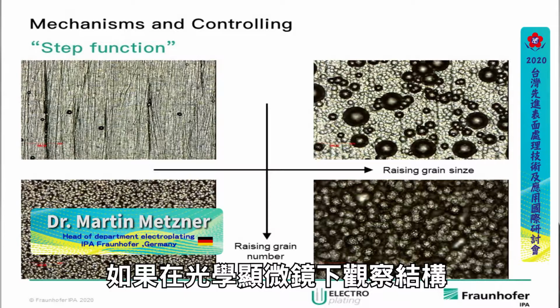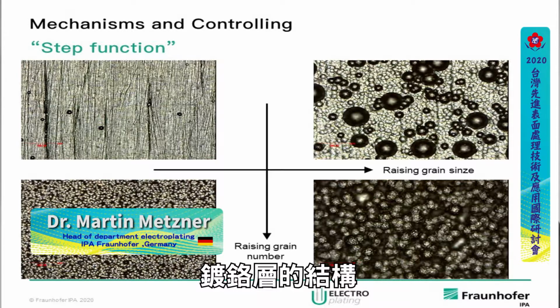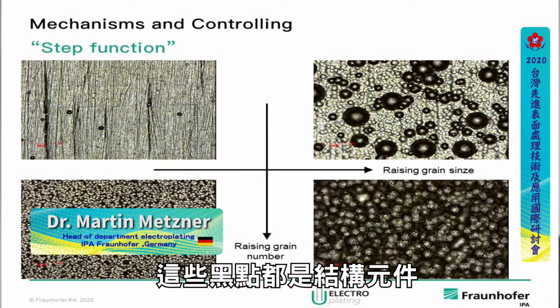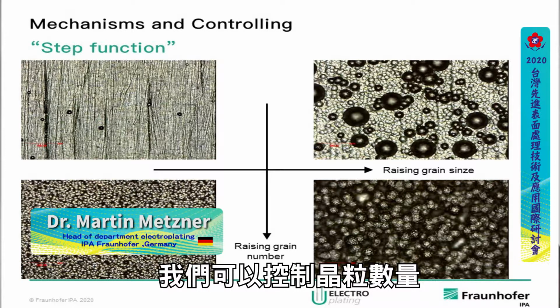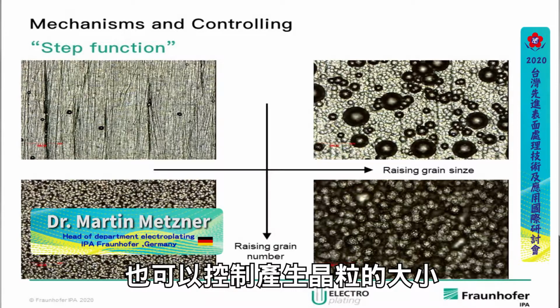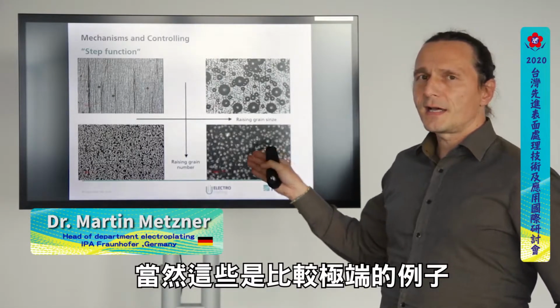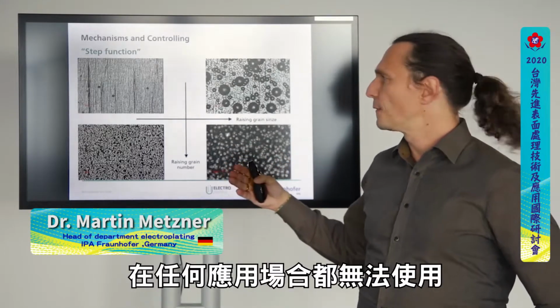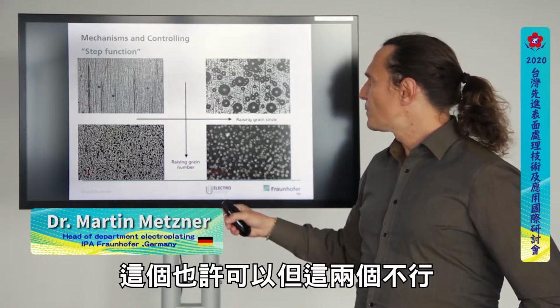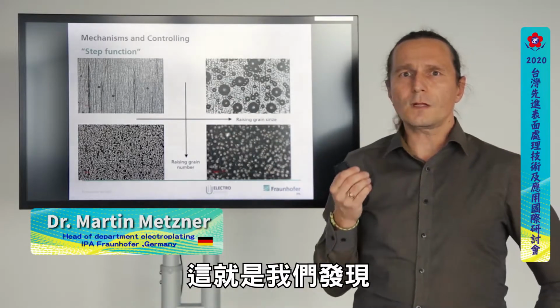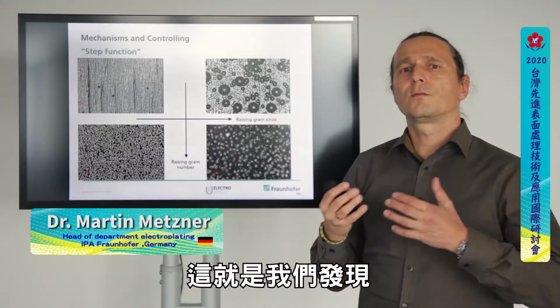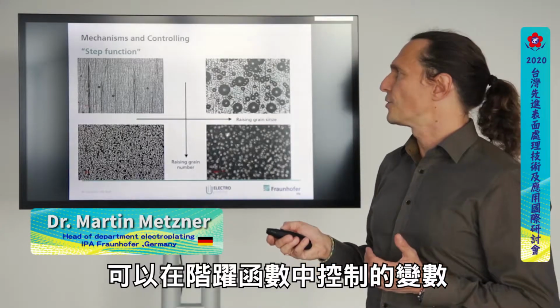What you see here, you look on the structure in the optical microscope, you look on the structure of a chromium plated layer, and these dark dots are our structure elements. And obviously we can control the number and the size of these grains that we build up. Of course, these are extremes. This is nothing we can use for any kind of application. Maybe this one, but not this or this.